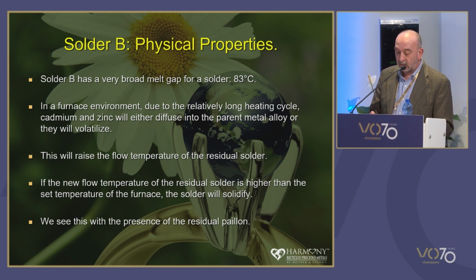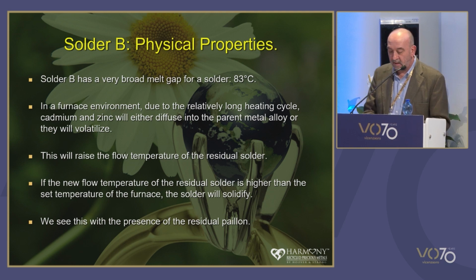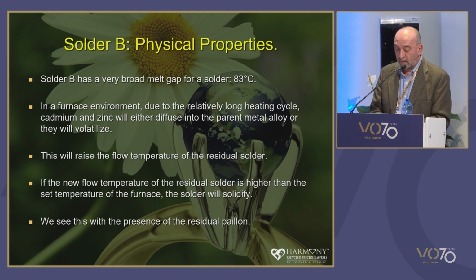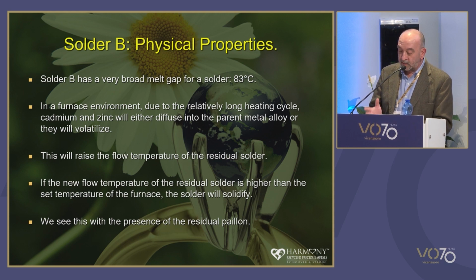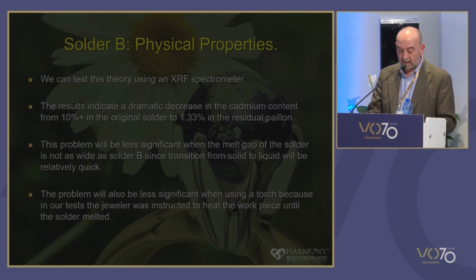The new melt temperature or flow temperature of the solder might be raised sufficiently so it's above the set point of the furnace, so it's no longer going to melt or perform as intended. And that's probably why we see the residual piece on the furnace soldered test.